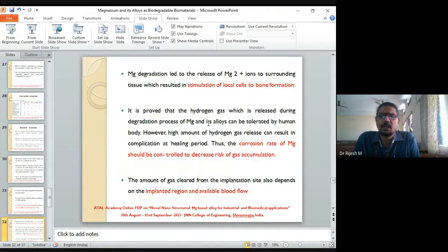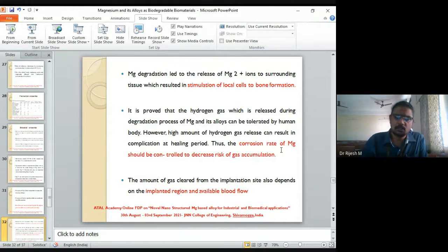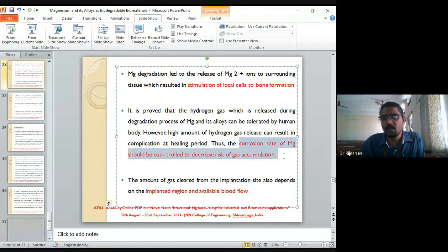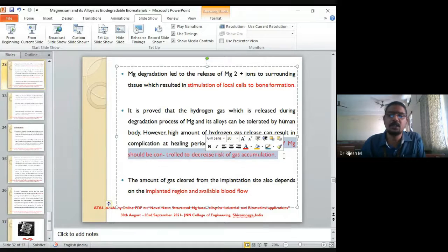But if the amount of hydrogen gas release is very high, you will have complications in the healing time. So corrosion of magnesium should be controlled to decrease the risk of gas accumulation. That is very important. So the majority of the work in biodegradable materials should concentrate on controlling the corrosion rate of magnesium alloy.